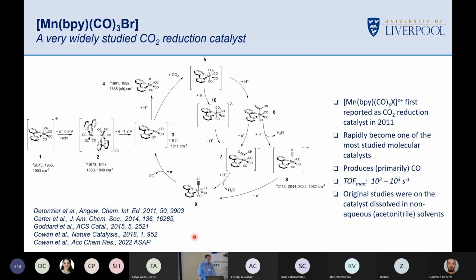We thought it would be interesting because one of the things we noticed when doing the surface spectroscopy and also other studies was that we generate the catalyst in a reduction step, this active catalyst, and it's got two possibilities. It can be protonated to a hydride, or you can bind CO2 and rapidly protonate down this pathway.